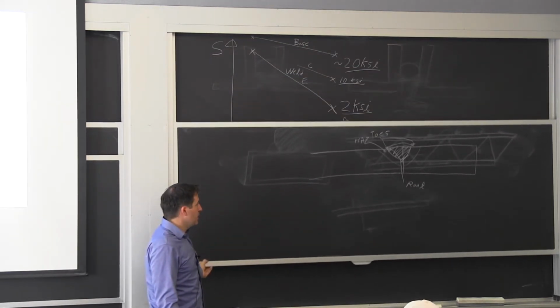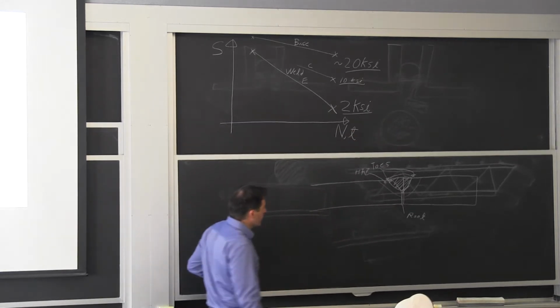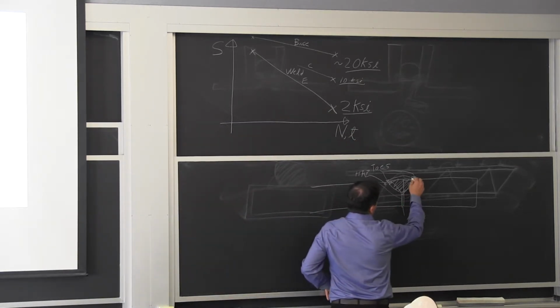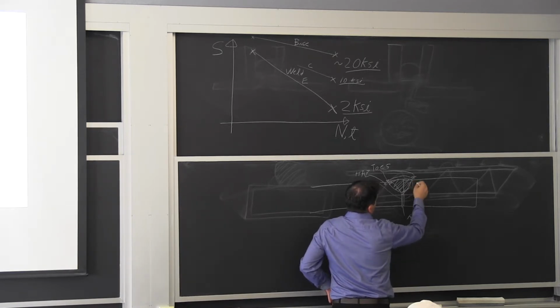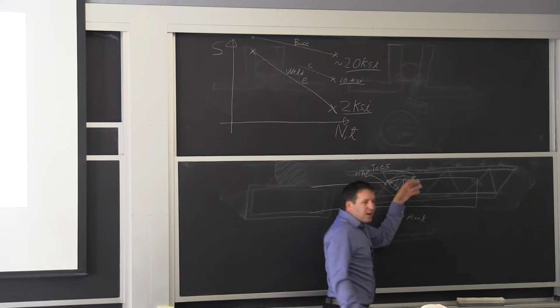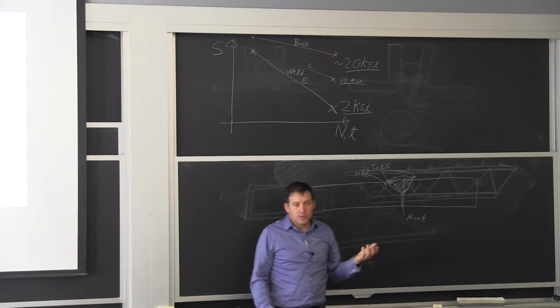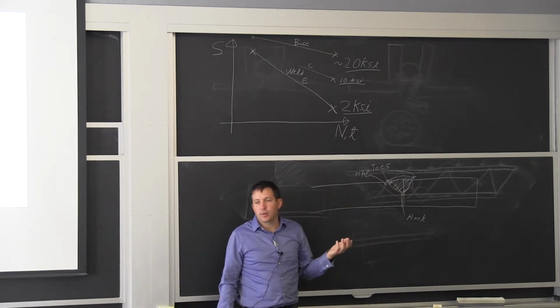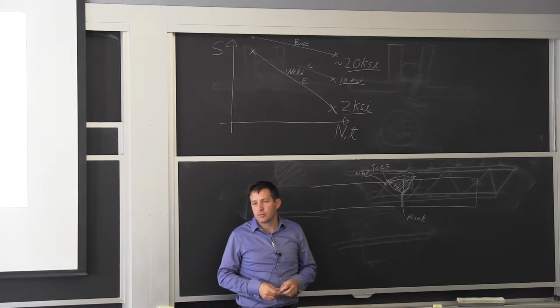And that's why, if you could start a crack here in this high tension zone, right at the toe of the weld, which is very, very typical, right here, eventually I'm going to fall outside that zone of residual tension, but I already have a crack, so the crack is going to continue to grow. Well, we covered a lot.